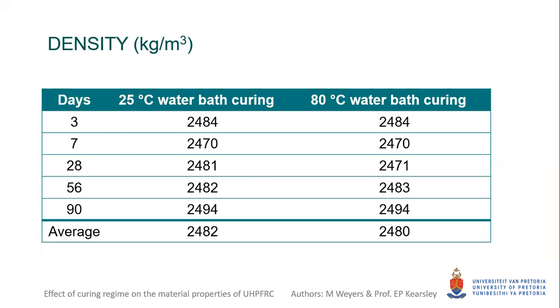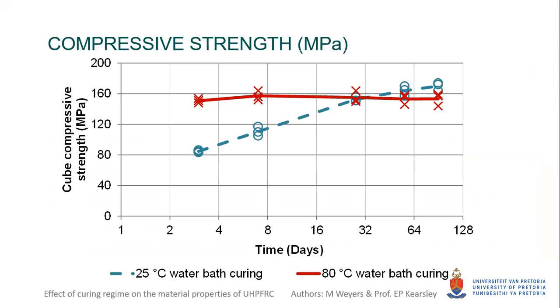The average cube densities obtained are tabulated. The difference caused by curing conditions was deemed insignificant. This illustrates that thermal curing has no effect on cube density. The cube compressive strength was measured by testing 100 mm cubes, and the strength development over a period of 90 days is illustrated in the figure.